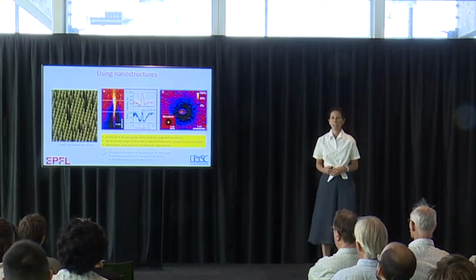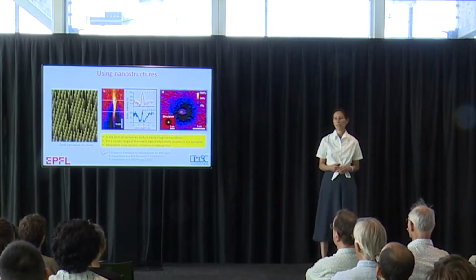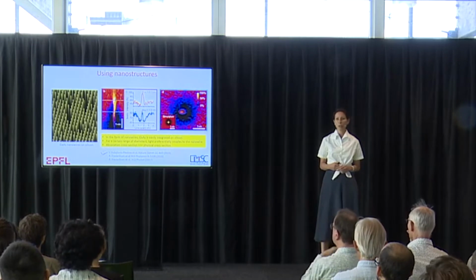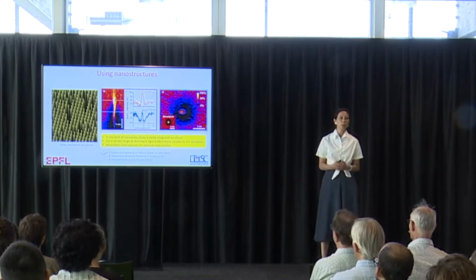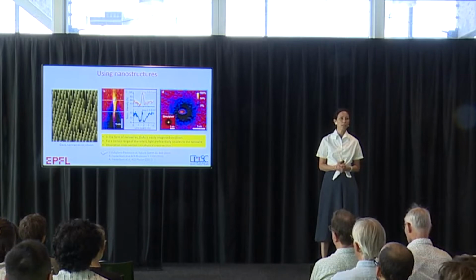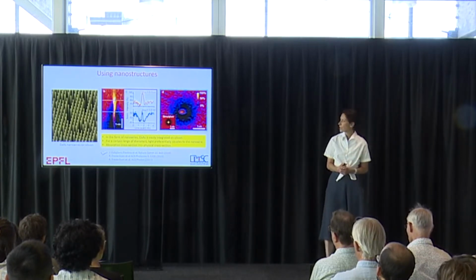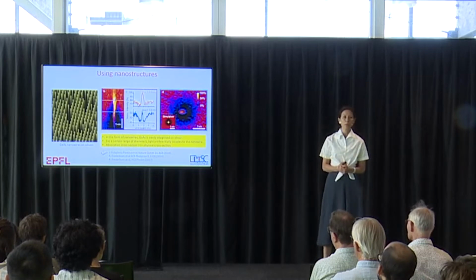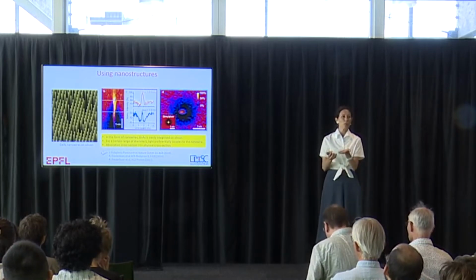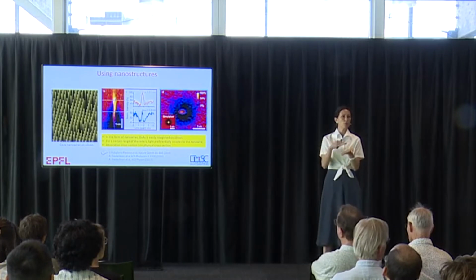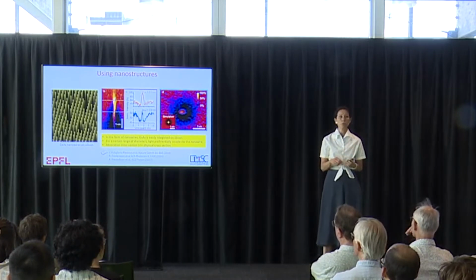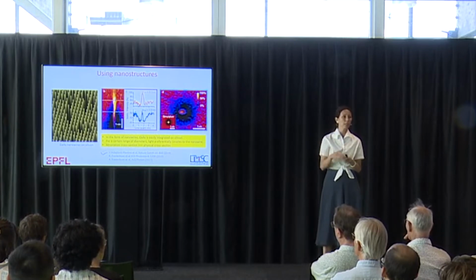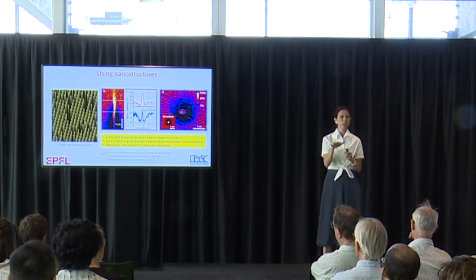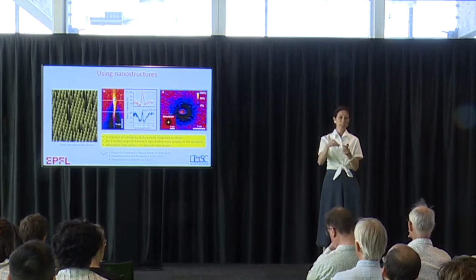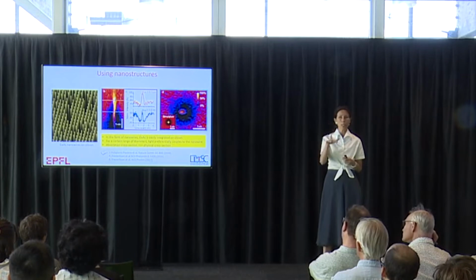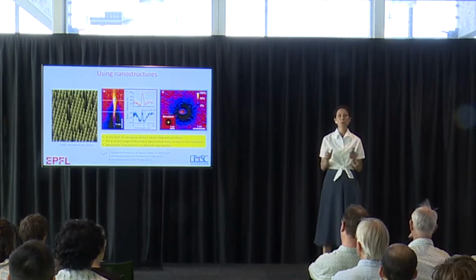This is work we did with Esther some years ago, which elucidates what effects happen with III-V nanowires. So not only do you economize material, but there are also some effects that make you absorb a lot of light. And the experiment we show here is one of my favorite experiments, I have to say. You put the nanowires in a solution, and you try to image them with a confocal microscope. The confocal microscope is there to map where the photons are when you illuminate. And to do this, you have fluorophores in the solution that emit light every time they get a photon on them. You can illuminate with different wavelengths, and with this you map where the photons go.